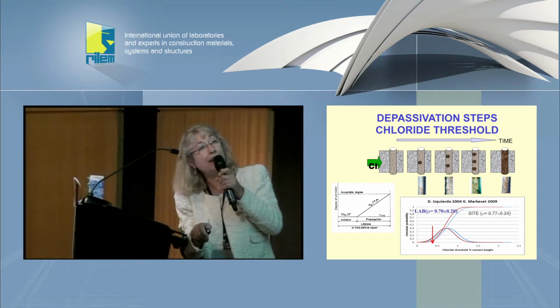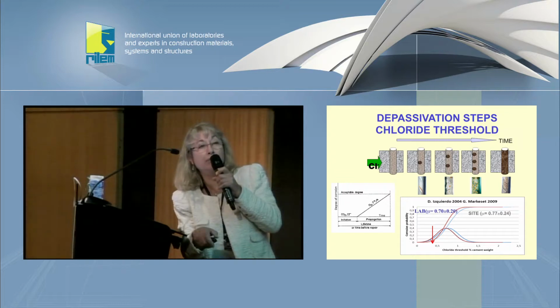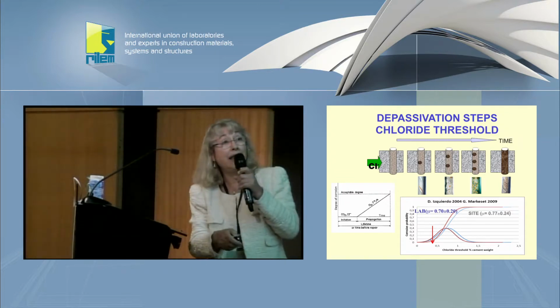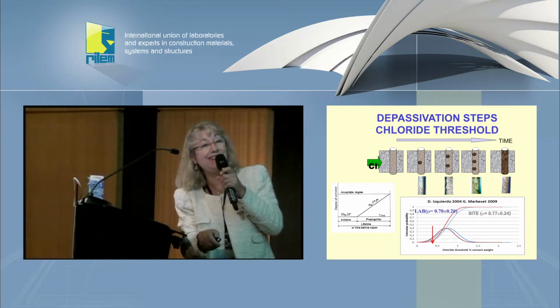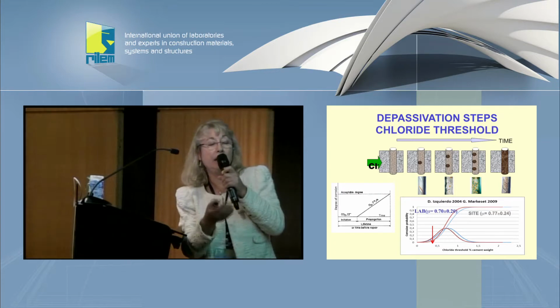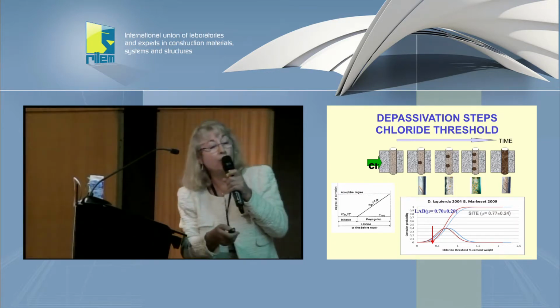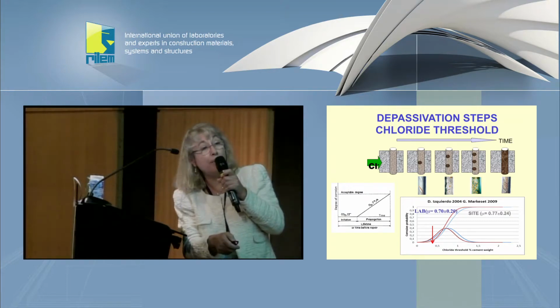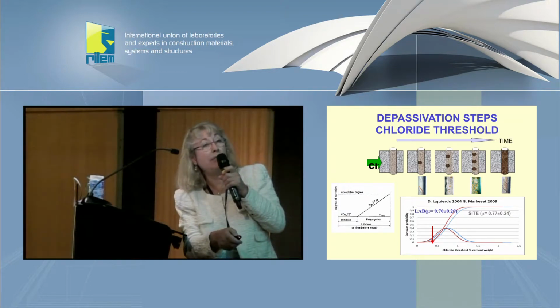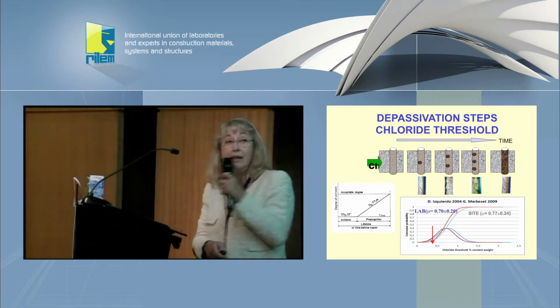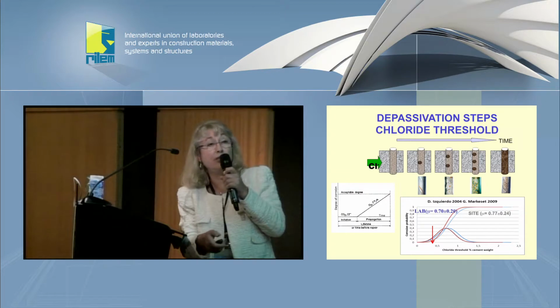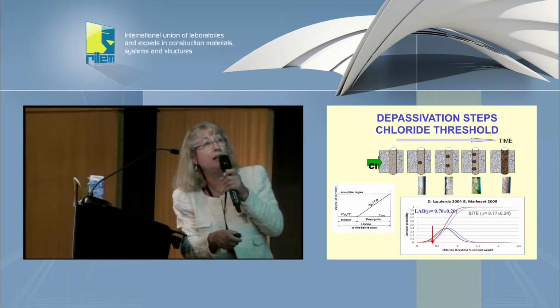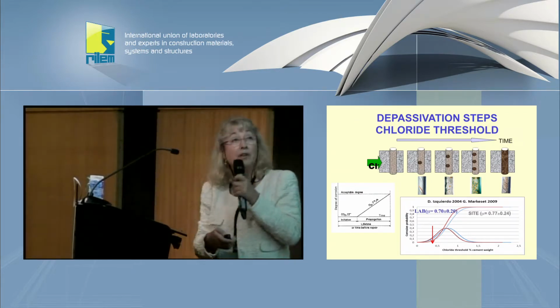I just put here in red the distribution we found in mortar specimens in the lab, and this was found by Markeset in the real bridges in Norway, and they are so close that we can say that this is a general distribution for bridges, at least in the aerial part, and we see that the 0.4 that we are typically using is giving about 10% probability of failure. In that case, taking a 0.4 as the usual value is conservative, is correct, is to say that it will be about 10% probability of depassivation in the time we are considering.